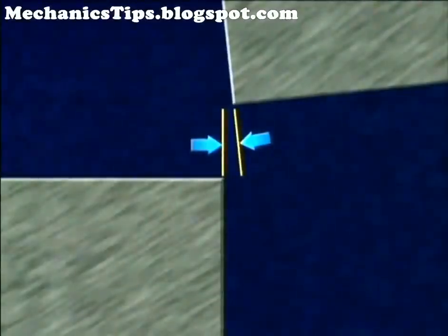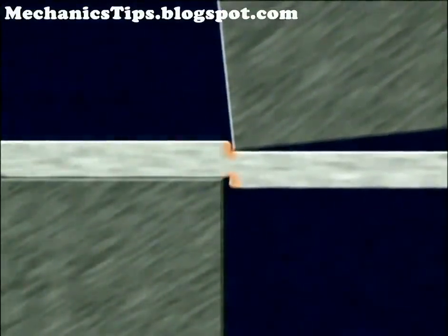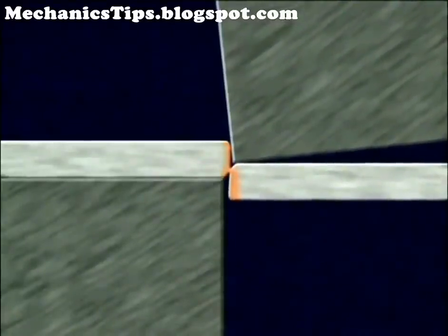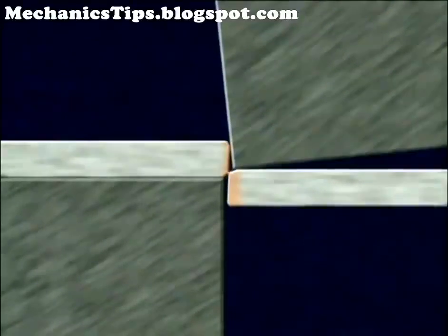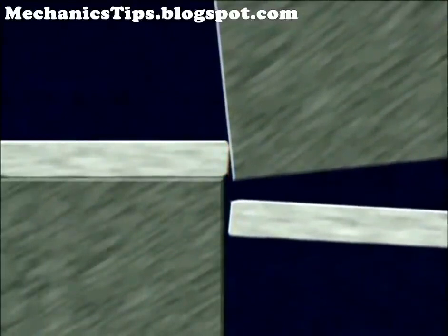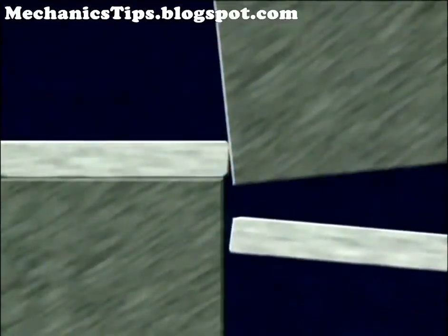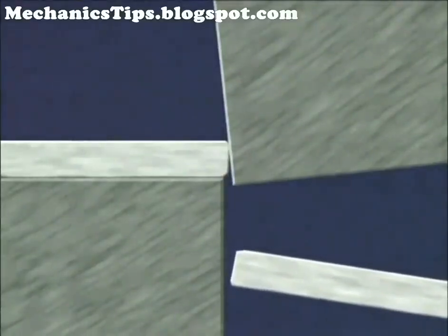On most shears, the upper knife is aligned at an angle to the lower blade of between 1/2 and 2.5 degrees. This angle helps concentrate the shearing force in the exact area of blade engagement between the two knives and starts the fracture on a straight line parallel to the surface of the knives. This inclination also causes the upper knife to move away from the lower knife during the shear. This ensures that the sheared workpiece, called the drop, will not become wedged between the two blades.